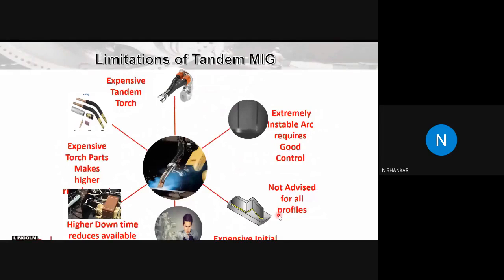Now, can tandem be used in all places? No. Why is that? I'll tell you. Tandem does not find extensive application for various reasons. When you have two arcs happening in the same weld puddle, you need to have an extremely good feedback system to make sure that there is no arc interaction or magnetic arc blow which will affect the quality of the weld. The torches are special torches, so the parts are expensive, therefore the running cost is going to be high, and also the tandem torch is a little bigger. It cannot reach all joints. It has got a constraint.